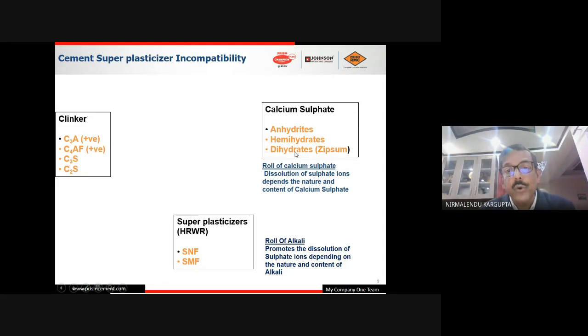If we go with dihydrates, your cement may quick set or flash set. So you need to go with some combination of anhydrates and hemihydrates, because your rate of dissolution has to be increased. Otherwise, it's very difficult to maintain the workability.